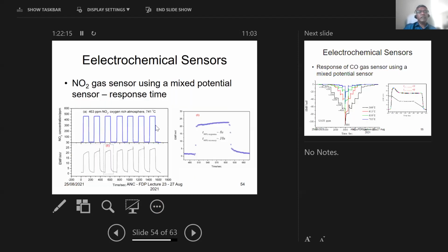Similarly, this shows the response from the sensor. So we have spiked the sensor with nitrogen dioxide several times, and we have recorded the response, and you can see that the response is fairly consistent from the sensor. And this particular graph on the right shows the response time, for stepping up the gas concentration. The response time is about 8 seconds, and stepping down is around 10 seconds to come back to the original value. Okay, so that is excellent. I think 8 seconds and 10 seconds is fairly good.